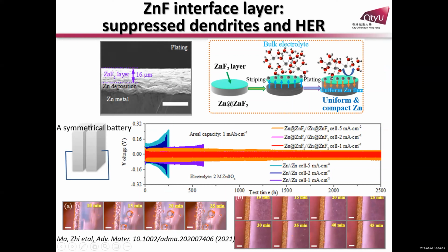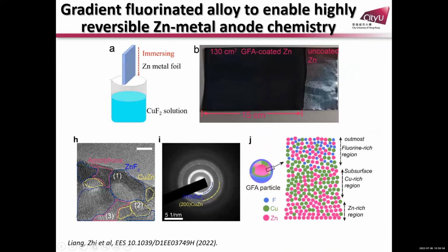If you have this coating, there will be no more hydrogen evolution. So if we use a conductive coating, it cannot avoid hydrogen evolution, but it can be good for kinetics. If we use an insulating coating, we don't have hydrogen evolution, but we will sacrifice kinetics.